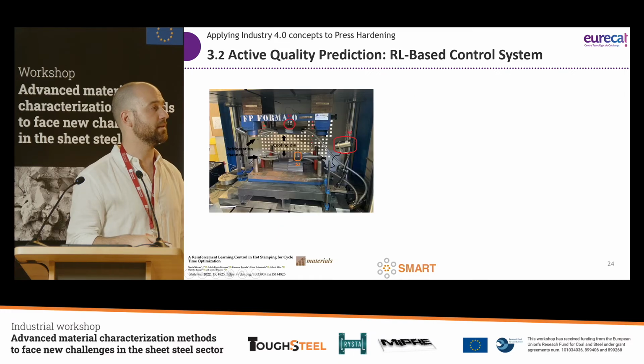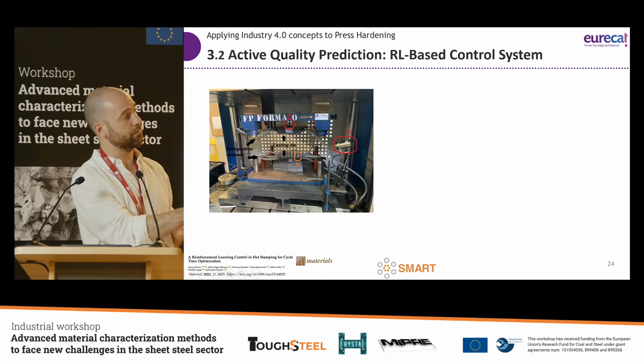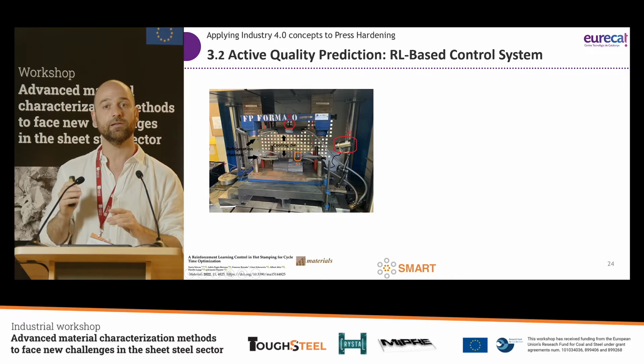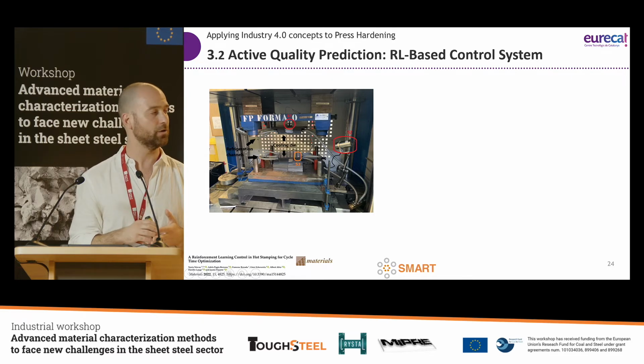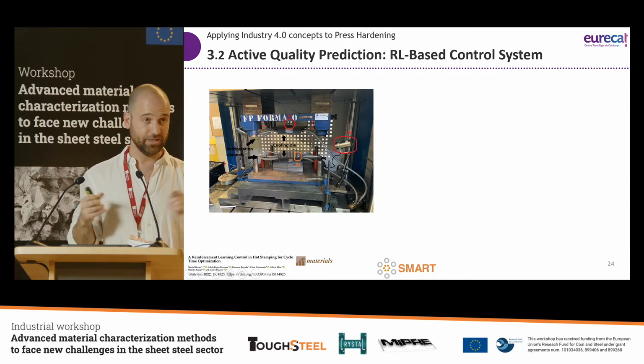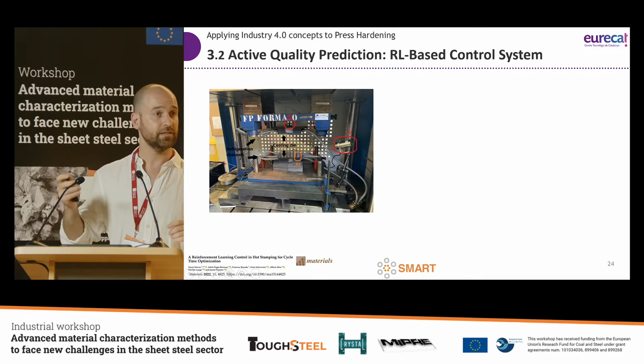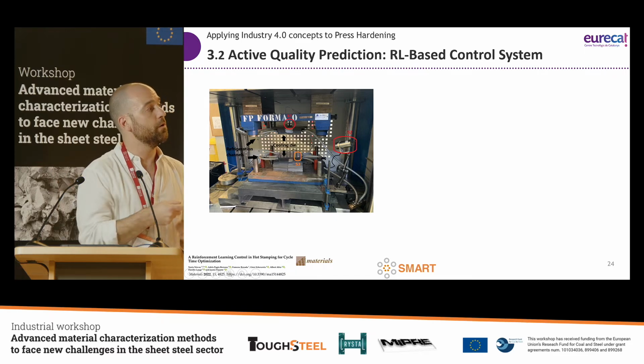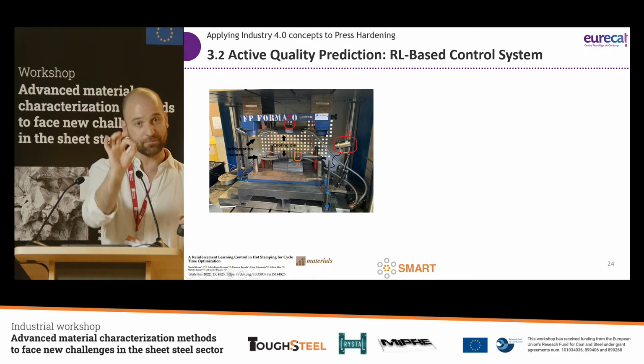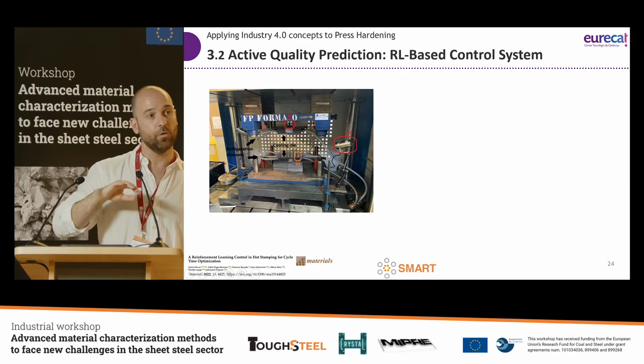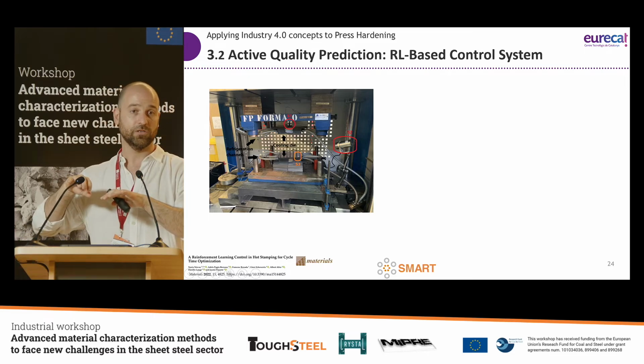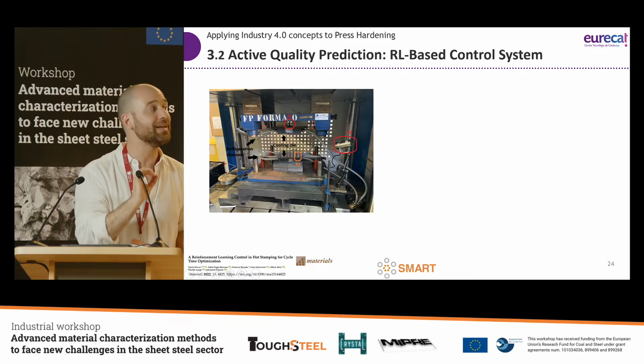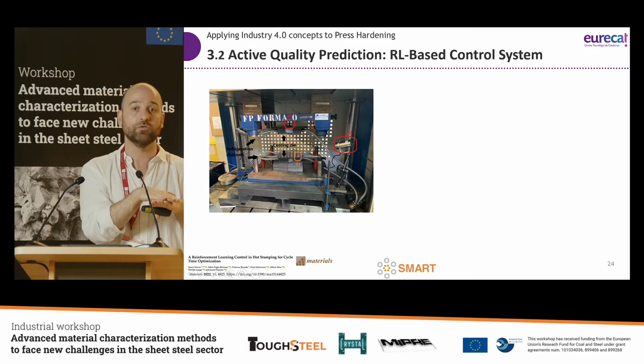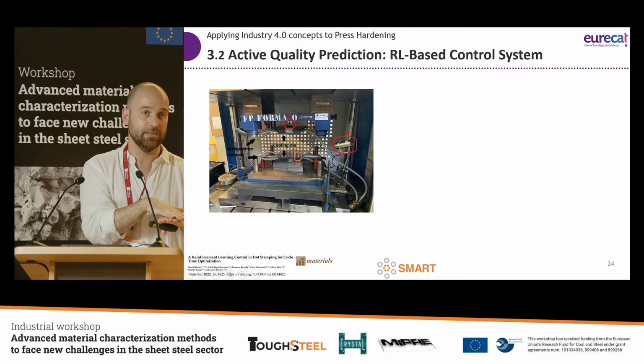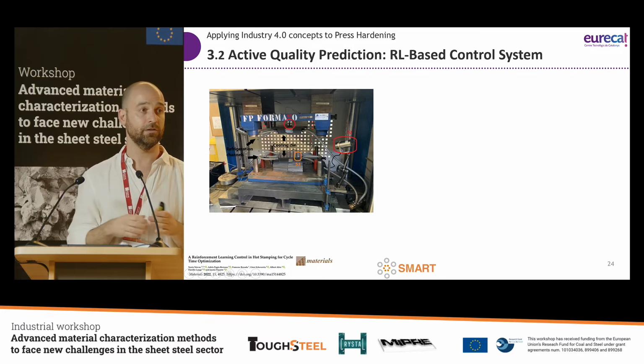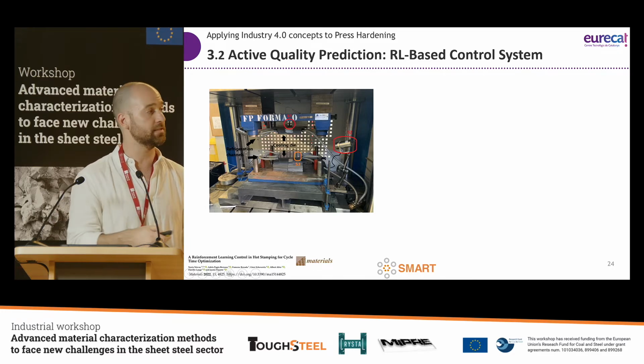A real line is a real physical system. And we went back to our physical system, and we started doing some trials. And what we did was something to behold. We were taking sheets from the furnace. So every 30 seconds, we took a sheet from the furnace. We put it into the die, and then we noted the temperature at the beginning, the temperature of the dice. We input everything into this control system, and this control system proposes how many seconds the dice need to be closed for the temperature not to reach the uncontrolled threshold level of 160 degrees.